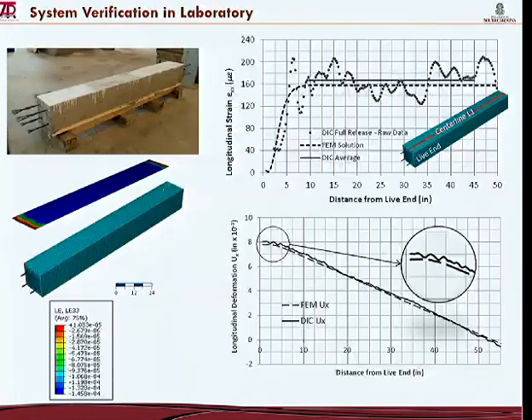with finite element analysis of that same specimen. This graph shows the longitudinal strain once again along this line as a function of location from the live end of the specimen. The solid line is the average, is what the finite element predicts at the constant section, whereas the dashed line is the average. I'm sorry, the dashed line is the finite element solution. The solid line is the DIC average value of this data here. And when we look at the displacement, the longitudinal deformation up to the midsection, this is pretty much what we captured here, we see the accuracy of the method.